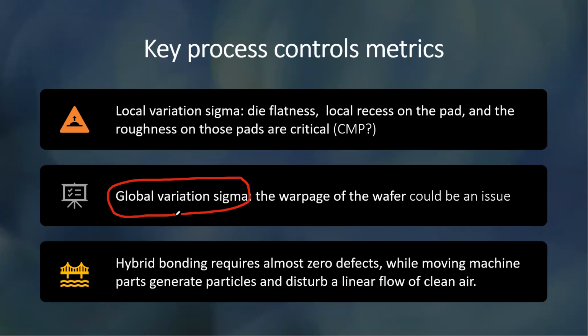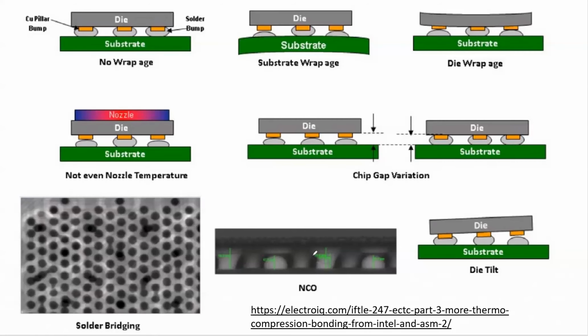All right. When the sigma is... which means that for the process window, 3 sigma is what you would like to control, and then 5 sigma is the range that you would like to control. So all these have to be controlled, right? Mechanically they have to be controlled. If you don't control it nicely, you have bridging. This is solder bridging, but you can imagine copper pad bridging in hybrid bonding.